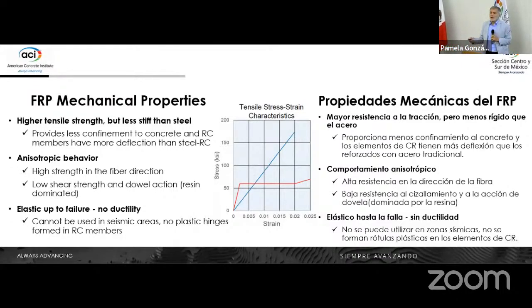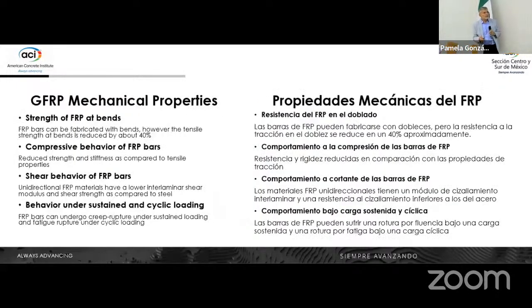In terms of strength, if you take a grade 420 MPa steel, the bread and butter of our industry, we have a strength that could easily be 2.5 times that, but the stiffness is less. It's a material that is anisotropic, properties in two directions are different, and, a very important property, it is elastic to failure. These are implications, if you go into seismic design, that are obviously of significance. The strength of the bends is less. This is perhaps one of the weakest points. The compressive behavior is also less than the tensile, and the shear behavior is different from what you are used to with steel. And then under sustained load and cyclic load, we have a phenomenon that is called creep rupture.